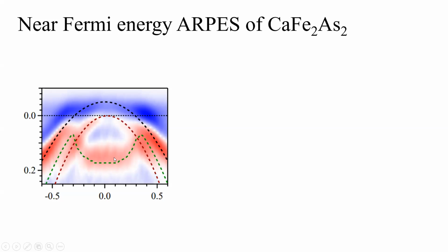I mean, we didn't put any reduction in symmetry of the compound while doing the electron structure calculations. So this part we don't expect. So it means that this part is coming from something that we did not include in the calculation. That part is basically the antiferromagnetic ordering, which is difficult to put in the DFT calculations. So based on those things, we are saying that this part is coming from the antiferromagnetic ordering and the back band folding of the beta band. Okay. Thanks.